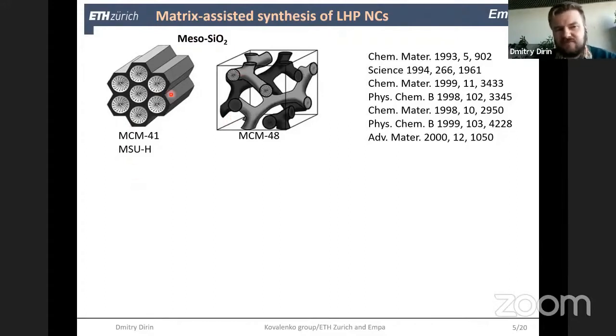At first glance, this is an ideal matrix to grow nanoparticles, because then you can have very monodispersed nanoparticles. But in the case of cadmium selenide and many other conventional semiconductors, people could grow nanoparticles but never achieved any good emission, because nanoparticles in this case have a lot of dangling bonds. Their surface is not passivated at all.